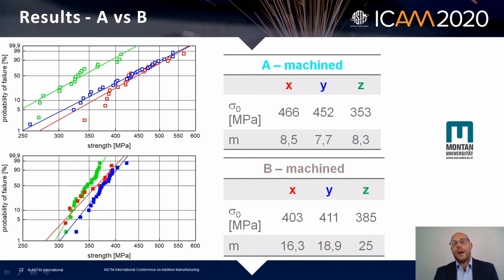So you're achieving quite high strength values, but the Weibull modulus is rather low, and the Z has a significant difference from X and Y. So again, why does this happen? Because we have smaller grain sizes, but the defects are still here, and when you test them, you can then find them more easily. And the B samples have a lower value in strength but a higher Weibull modulus, and there is no significant difference between all three axes.